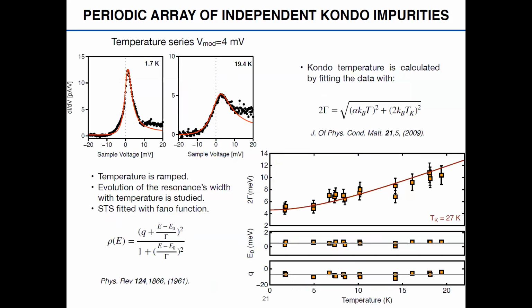And then we've also studied, as is typical in this system, the Kondo temperature of our Kondo impurity. To do this, we have to measure how the full width at half maximum behaves as the temperature is increased. So we perform variable temperature measurements. The Kondo resonances are fitted with a Fano function. This is this one here, where gamma is the full width at half maximum. And then if you plot the values of the full width at half maximum as a function of temperature, with this equation here, you can calculate the Kondo temperature. In this case, it's 27 Kelvin, which is in good agreement with our previous results that at 52 Kelvin, we didn't see any Kondo resonance.